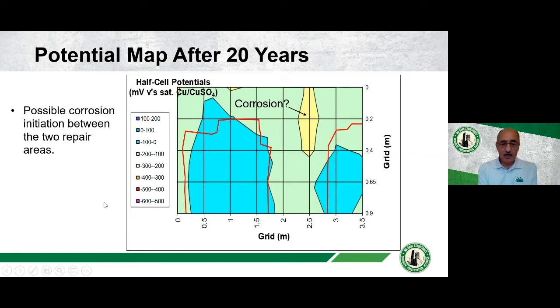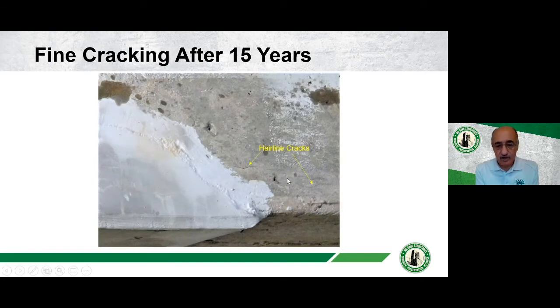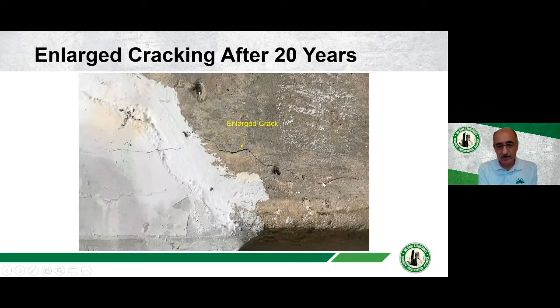Actually looking at it, after 15 years, although to be honest, I hadn't noticed it at the time, I was taking regular pictures and looked at them later on, and I found that there's a hairline crack in the 15-year photograph. It's just beginning, which coincides with the time when our current density had dropped. So maybe corrosion was beginning to happen here. We were no longer able to prevent corrosion from happening. That hairline crack grew into a larger, continuous crack that eventually got into the patch repair itself. This is the one patch repair. The other one is down here somewhere. So in between the two, which is away from the anodes, the nearest anode will probably be down here, and that's, I would say, at least 300 millimeters away. So it's lost enough power not to be able to protect that region.